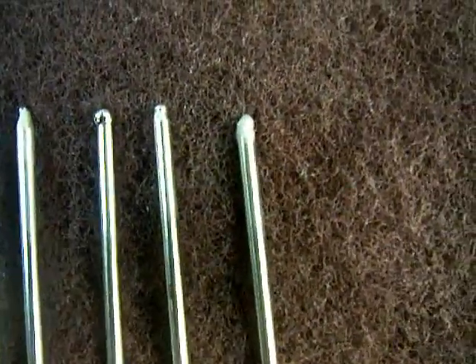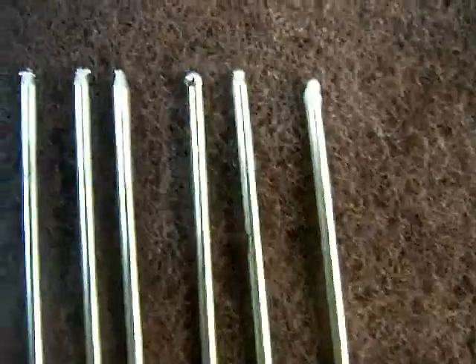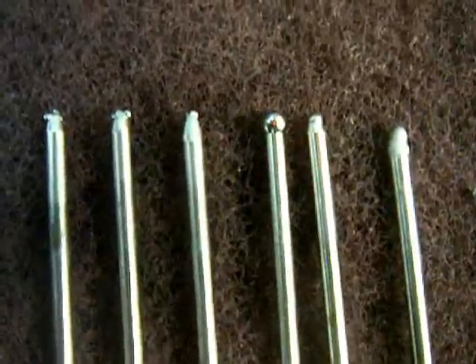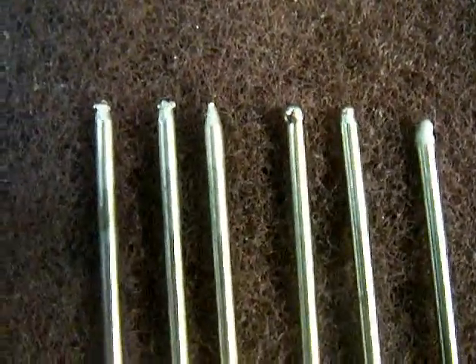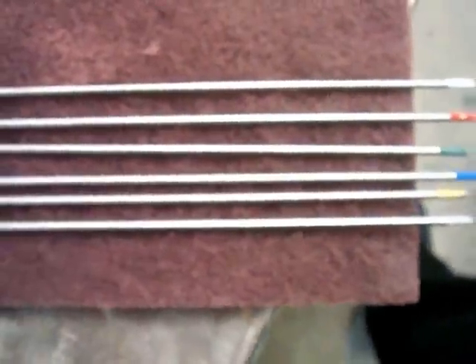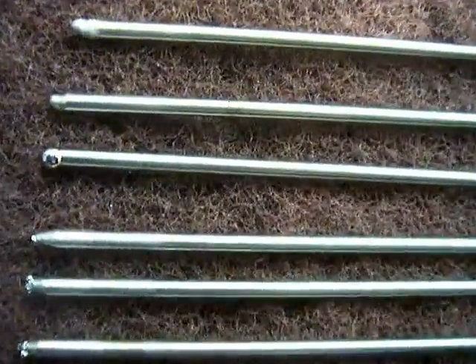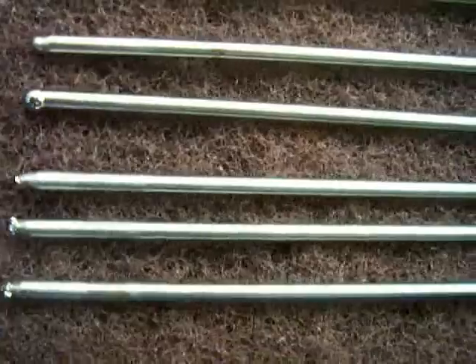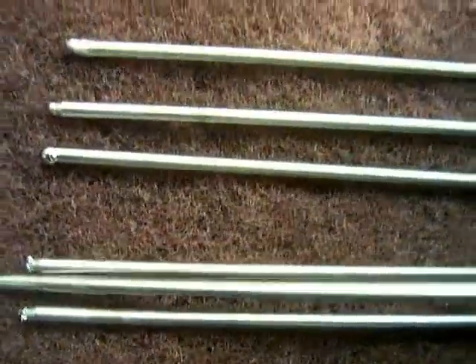The 2% thoriated held up well to the amperage but didn't ball as evenly as the lanthanated did. And the zirconiated just kind of balled crooked and was kind of unstable. Didn't handle the current well. If I'd have been at a lower amperage, the pure and the zirconiated probably would have fared a whole lot better. But I'm testing the ability to carry amperage on this test. That's really all. So the 2% lanthanated, clear winner.